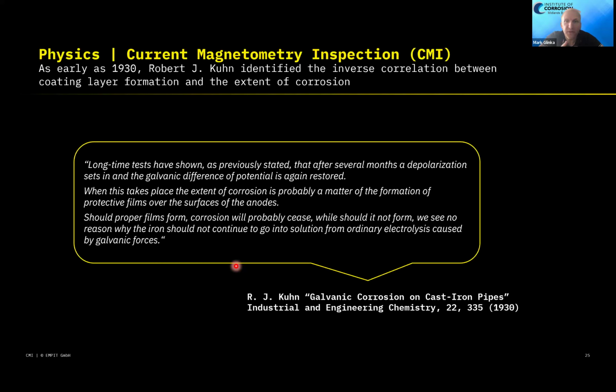Okay, so this dude actually managed already in 1930 to see that when we have proper films we have no problem, whereas when we don't have passivation layers, we do suffer or may suffer active corrosion. So that was for us the big bang, and we were thinking, oh, maybe we can measure this in the lab. And you can see the data over here.